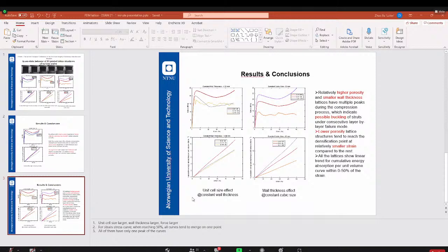As compared to other 3D printed structures from FDM, for example, internal voids are one of the big issues for the 3D printed lattice, especially for parts that have complex curves and geometries, because you can see the path from the nozzle. Even though we tried our best to optimize the process parameters, the infill rate is still not really 100% yet. So yes, internal defects or internal voids are one of the major issues.